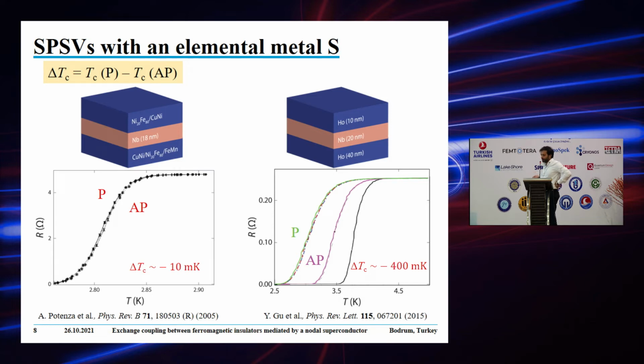It's of the order of 400 millikelvin, and this now starts becoming an interesting number, because these two states are well defined, and you have two robust logic states, if you want, against thermal fluctuations in the system. Thermal fluctuations are certainly not of the order of half a Kelvin, so you can really think of encoding information associated to these two states. And of course, in the following slides, you will also see that it's possible to estimate the delta Tc from this measurement of resistance in the parallel and antiparallel states.